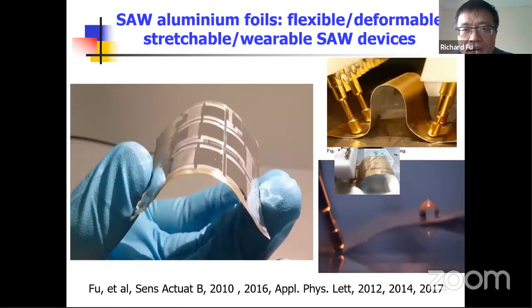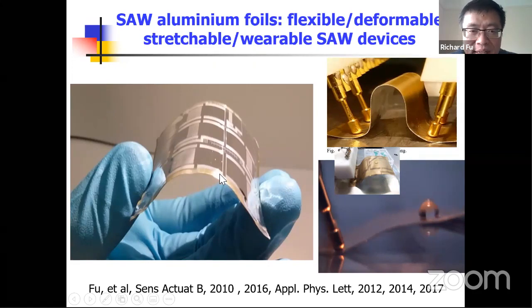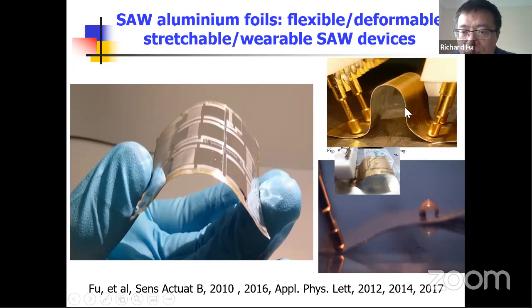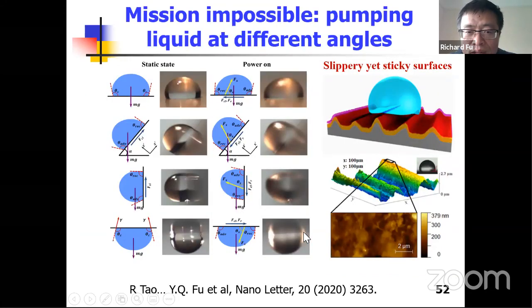Then we found another flexible substrate, which is aluminum foil or kitchen foil. This foil is very thin, flexible, stretchable and easily deformable, so you can easily fix the shape. We deposit a thin film on it and then pattern it. Then we can realize the microfluidic function. Even when bending significantly, the signals are still very good. For wearable applications, the trouble is that when our body or hand moves in different directions, we need to make sure that whatever the direction, the droplet can still be actuated, but still stick there very well.